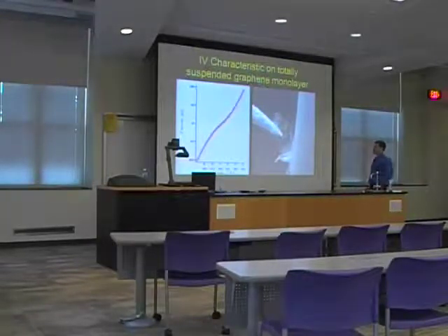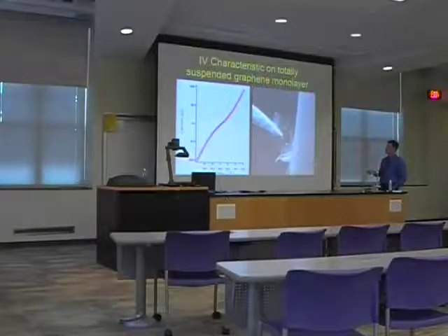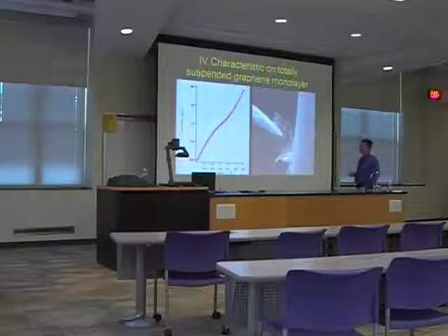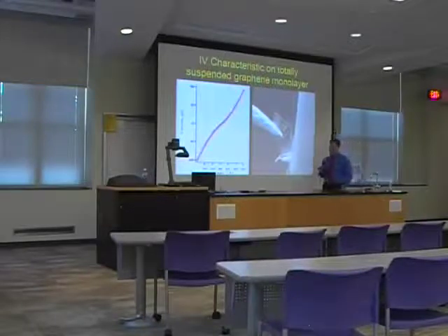Okay, this is a typical measurement. This is the graphene layer between 2 metallic probes. This is a monolayer in this particular case. Now this is the IV curve for this monolayer. You see a small effect of a Schottky barrier because graphene is not completely a metal. It's a semi-metal, or a very bad metal, let's say.